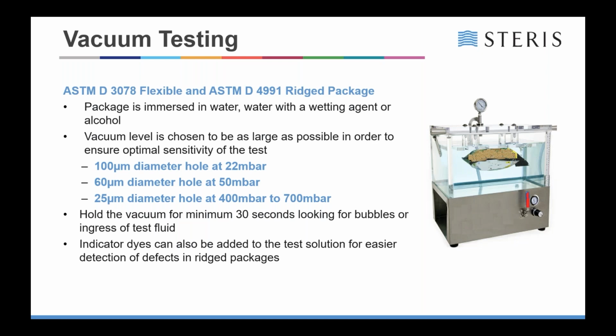You can detect different size defects depending on the levels of pressure that you apply to the package itself. Typically, you will find a 100 micron diameter defect at around 22 millibar, 60 micron at 50 millibar, and 25 microns somewhere between 400 and 700 millibar, depending on the material that you're testing, the pouch, the size, and the temperature of the water. If you're using something like Triton X in the water to reduce its surface tension, that's totally up to you, but you need to validate that yourself.